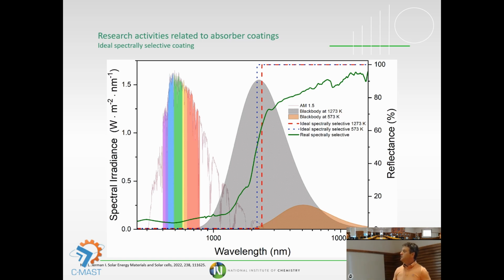And of course, as I said, we should absorb. This green line is one of our coatings for low temperature application. As you can see, it should have a really low reflectance, about 96-97% should be absorbed, and in the infrared region it should possess high reflectance. Just why? When you have a high reflectance in infrared, it means that it emits a low amount of energy, so you are losing a really small amount by radiation. For sure, you should fulfill the demand that you extract the maximum that is possible in order that it is feasible.